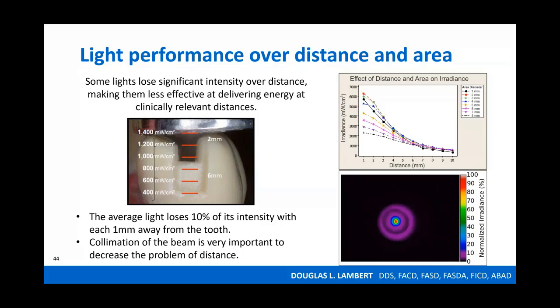And the little graph shows the intensity of that light through various sized orifices or apertures over distances of 1 to 10 millimeters. And the picture below shows the hot spot in the middle producing over 6,000 milliwatts per centimeter squared. But then as the distance increases, the intensity of that light, the irradiance of that light, drops to only about 500 milliwatts per centimeter squared. So this really shows the extreme variability of a light with a poor beam profile and poor collimation.